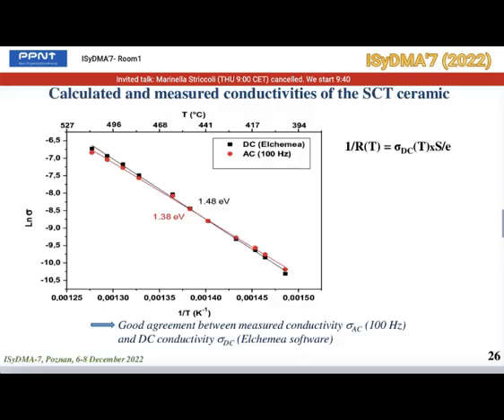Now, the DC conductivity of the ceramic is calculated from the resistance, thickness, and surface area of the ceramic, as you can see in the formula. We have plotted it as a function of the inverse of the temperature, as well as the AC conductivity measured at 100 Hertz. We note a good agreement between the two conductivities, which validates the calculations of the software.